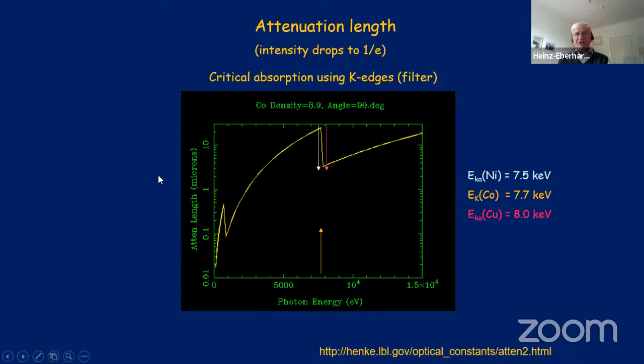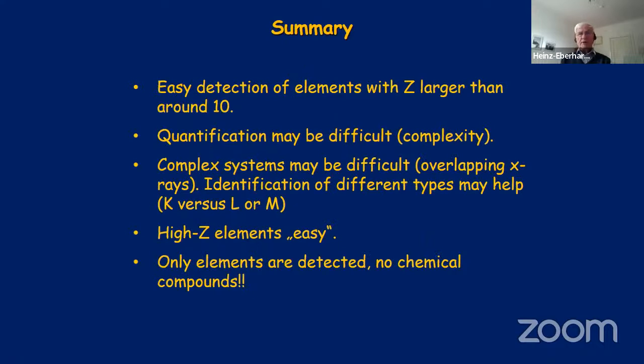With the nice feature of the edges, we can actually use the edges to filter out certain intensities in the spectrum in the case of X-ray tubes. That is done because of the absorption edges once you are over the binding energy of the next electron. In summary, it's an easy detection of an element. It's easier if the Z is large; it starts at around 10 and goes all the way up. The quantification is a little bit difficult. If you have a complex elemental composition, you get a superposition of K lines, L lines and M lines from the various elements, so the analysis might be a little bit tough in complex systems.